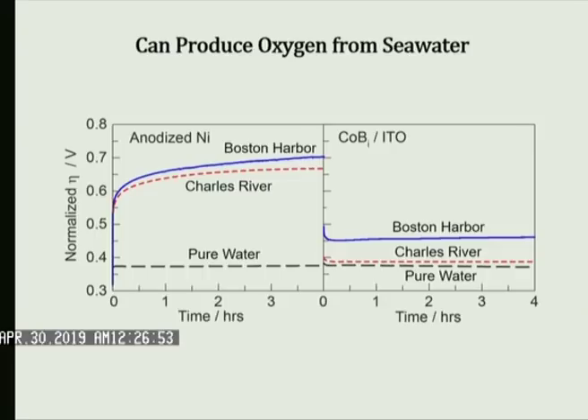So at 1.5 volts, we have a stable oxygen generation. This catalyst is nickel, for instance. If you want to do cheap water splitting, people will use nickel. But the problem is, once you go into things like Charles River, Boston Harbor, you get biofilms, and the catalyst stops working. And you can start to see you have to keep increasing the voltage, and then this thing isn't even stable. You can see it's drifting upwards. And that's literally because it's corroding and you're getting biofilm formation.